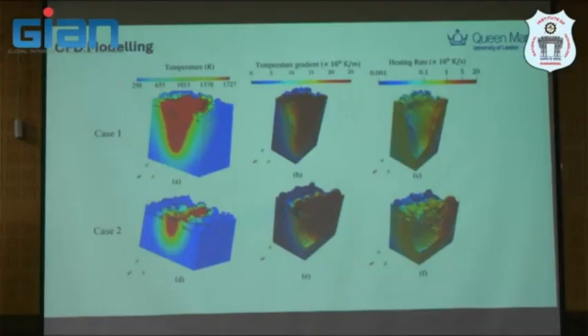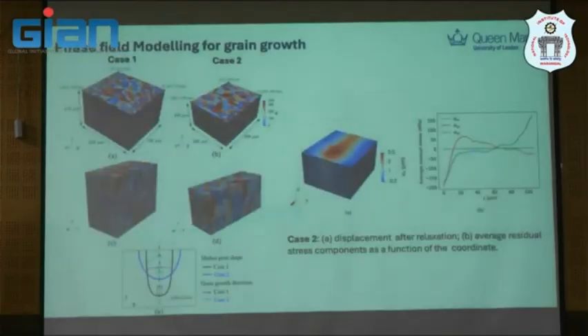They do two cases like me. If you remember my lecture on day 2, we talked about full penetration and conduction mode. They do the same. But the way they do it is they extract the thermal gradient, which is important for the microstructure model later. And then the heating rate. Why heating rate? That is a good question, but actually heating rate will tell you about the cooling, right? And then cooling is something we will use from this model as well, but this shows the heating rate.